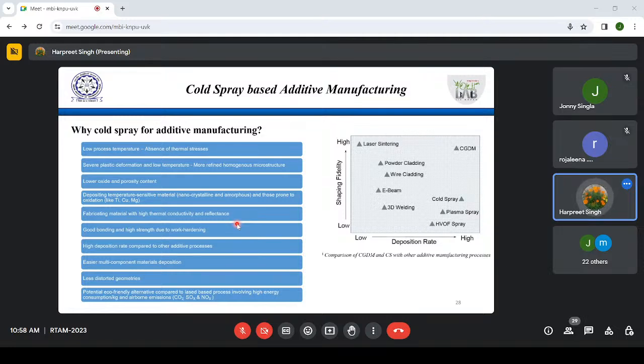So all those challenges are well taken care of in cold spray, because we don't have that concern of thermal conductivity as well as reflectivity. The material has mass, so it can be propelled, and it can be deformed. So thermal conductivity and reflectivity have little influence here. Good bonding and high strength due to work hardening: of course, you will get very good bonding and high strength, because the material is getting severely deformed, so you have strain hardening effects. High deposition rate.